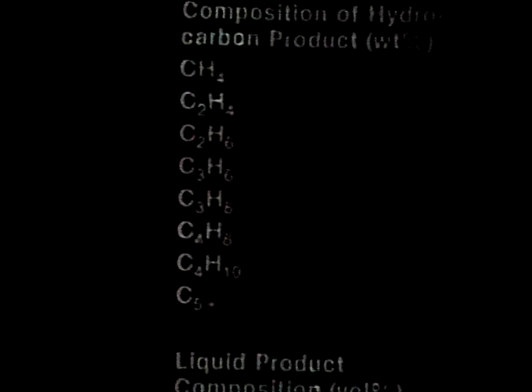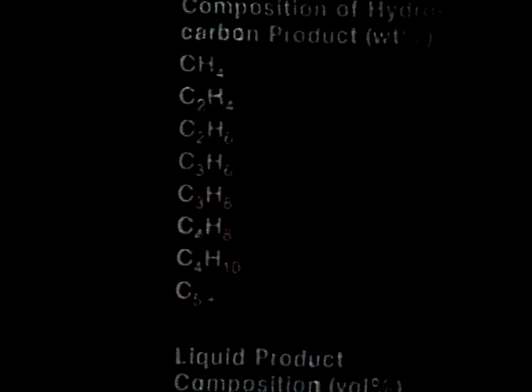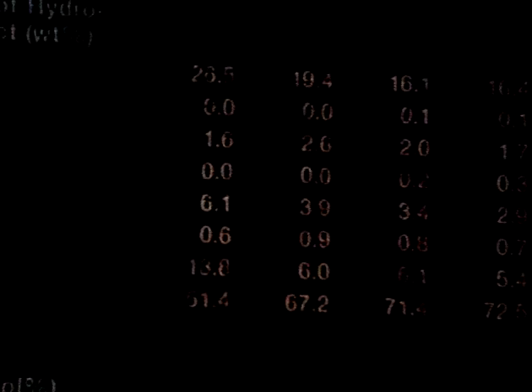Another big change that you find is in the reduction of the methane formation. This is the hydrocarbon product, C1 to C4 species here, and then C5 plus. You see when you add Thoria that there is a reduction in the methane yield from 26.5% to 19, and so on to 16. And the gasoline yield, C5 plus, increases from 51 to 72%. Nearly 90% of the C5 plus is in the gasoline boiling range.